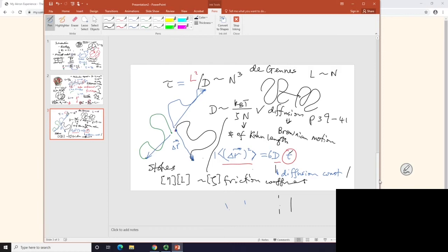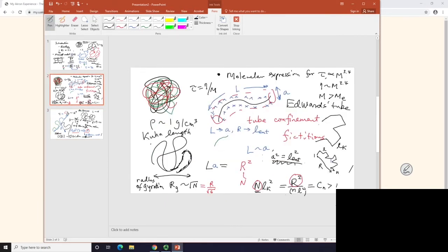And then it turns out the way he derived this works very well in the limit when the molecular weight is infinitely long. When the molecular weights are shorter, you have a fancy word, finite size effect. But basically the chains are less restrictive, if you like. That translates to having an effectively shorter tube. Therefore, in reality, the time is faster than the theoretical capture,